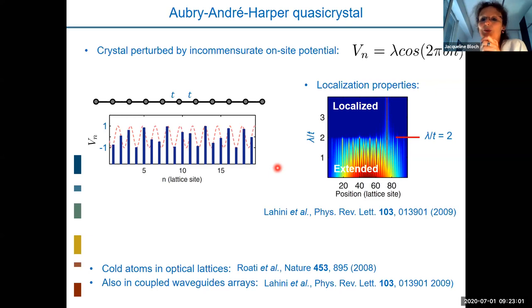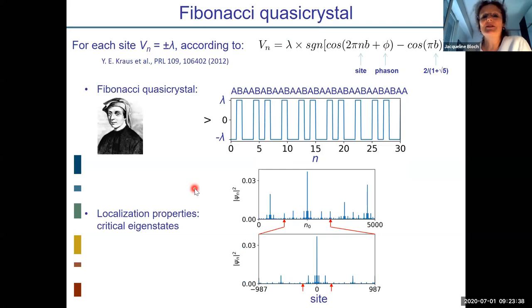So depending on this value of lambda over T, localization properties of waves inside this quasicrystal are completely different. When lambda over T is smaller than 2, all the states are extended, and so the system is metallic. It can transport currents. Whereas when lambda is larger than 2T, all the states are localized and the system is fully insulating. And in between, for lambda over T equal to 2, the system is really in between the two, and it is actually critical. The energy spectrum is fractal, and the localization of the states decays with a power law and is so-called critical.